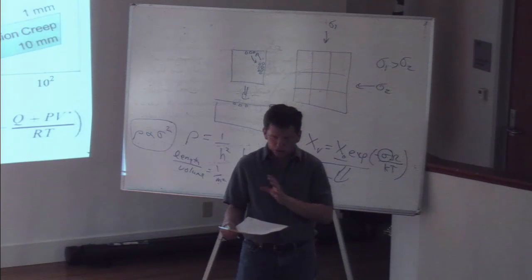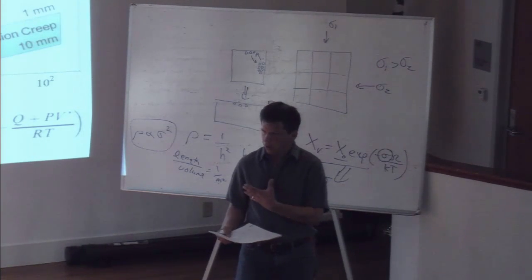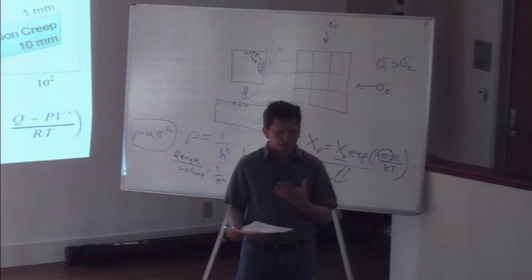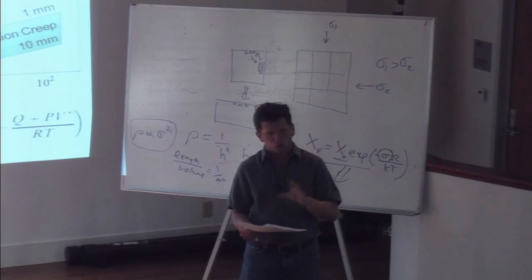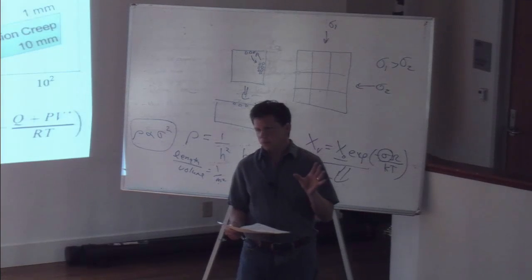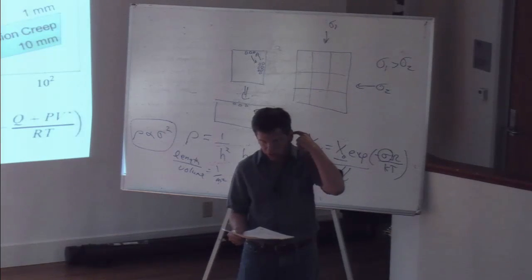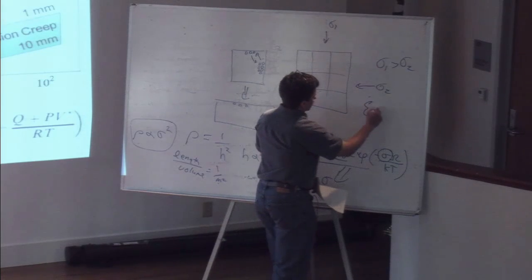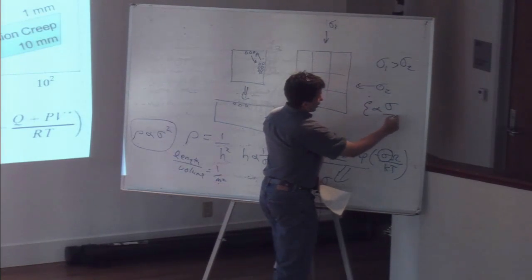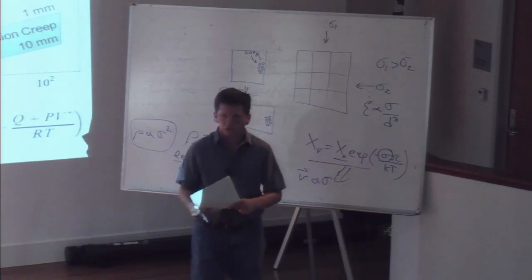And so, again, the concepts here, I could then go on for another 20 minutes, but just to get an insight that the strain rate is going to be dependent on grain size is an important point here. And it turns out that when the diffusion process that limits this is by grain boundary diffusion, which for all geologic materials so far studied is the case, the strain rate is proportional to stress and hugely non-linearly dependent on grain size. There's a cubic power here.